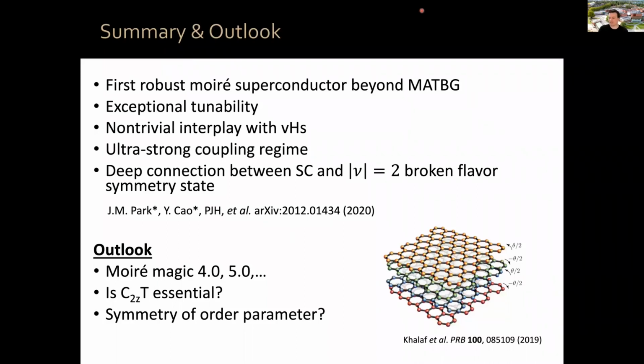So I think it remains to be seen in the bilayer case exactly if there is any violation of the Pauli limit or not, and if there is, by how much. And it would of course be interesting to look at this system. The fact that your Cooper pairs are very strongly bound suggests that the pairing gap could be very large in general, and your TC is determined by phase fluctuations. That could have interesting implications in terms of field, but it remains to be seen.